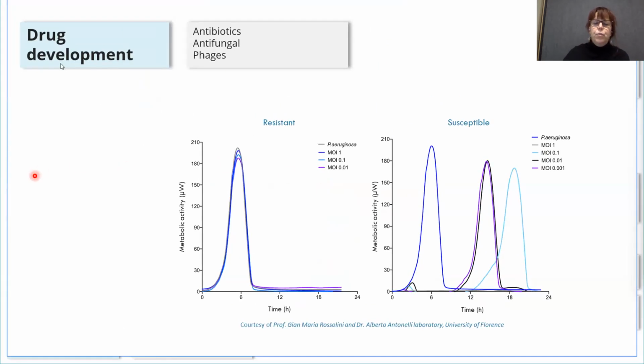Then another example for drug development, you could use it to look at antibiotics, antifungal drugs, or phages, as in this case. You can test different phages on different bacteria. In this case, there was a resistant strain with increasing amounts of phages added, but you see no effect whatsoever on the growth or delay in the growth of this resistant strain. If you have a susceptible strain, you can see that you're actually moving with increasing concentration of the phage in this case, and actually the highest concentration here is completely inhibiting the growth of this strain.